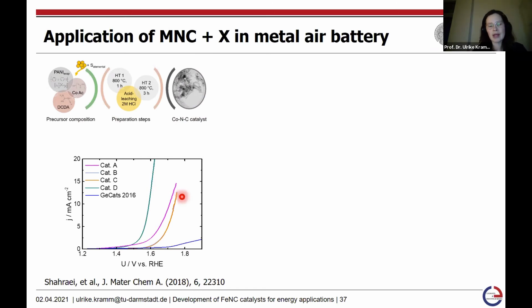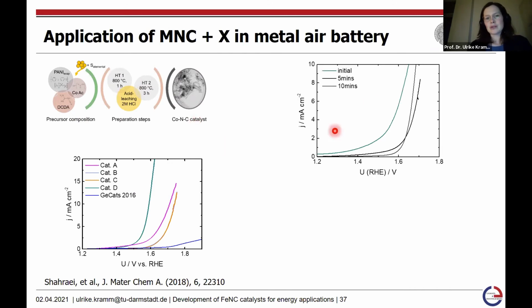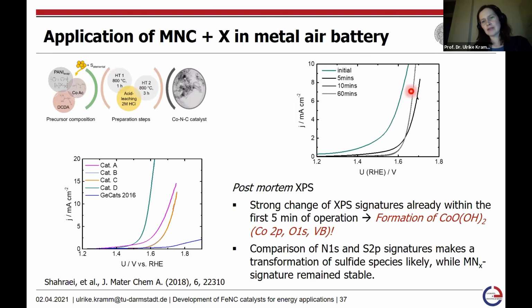So it does not only contain cobalt N4 centers, but also sulfides and metallic particles and oxidic species. And basically what it turned out was that these oxyhydroxide species are at the origin of the oxygen evolution reaction activity of the catalyst materials that were prepared here. This was based on postmortem XPS measurements. That means the catalyst was measured in the initial state, after 5 minutes, after 10 minutes, and then again after 60 minutes. And there we were able to identify these oxyhydroxide species within the catalyst material.